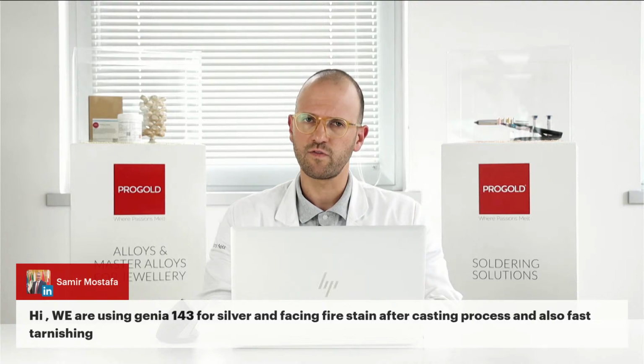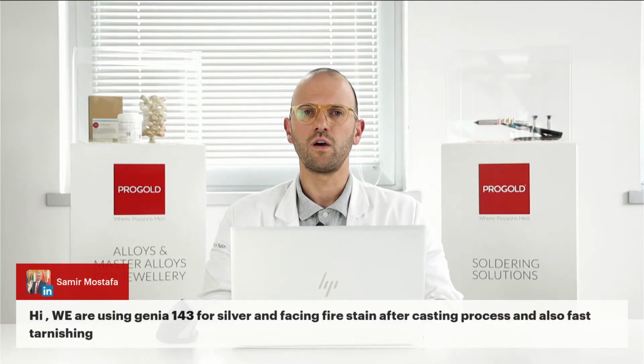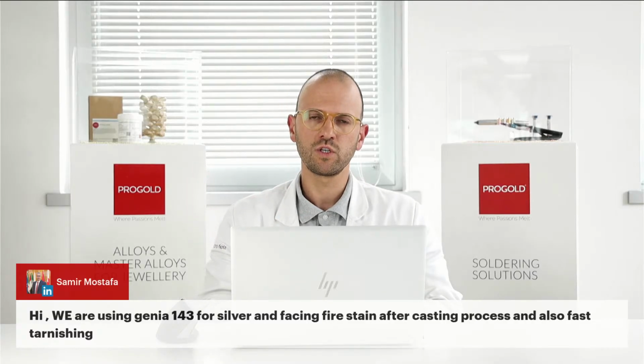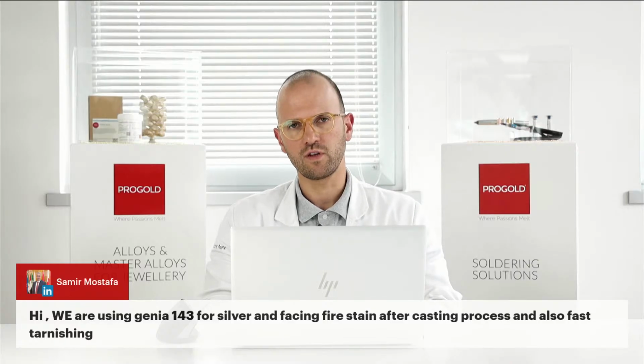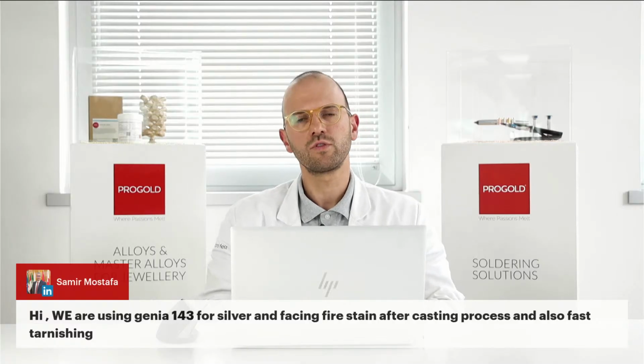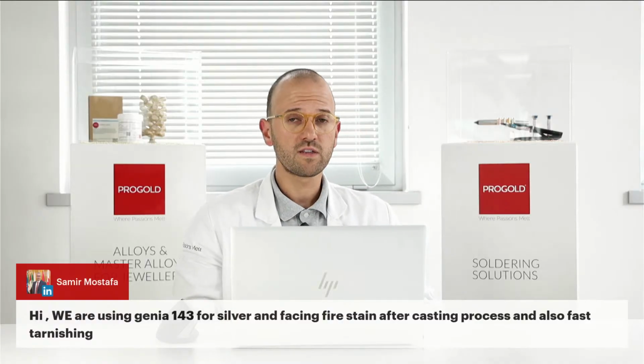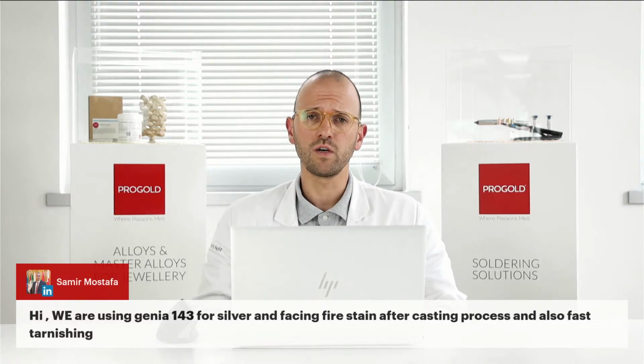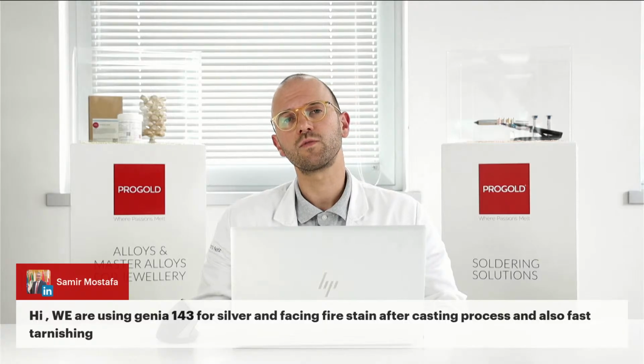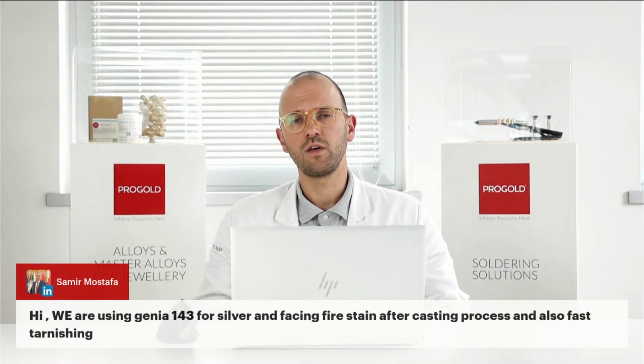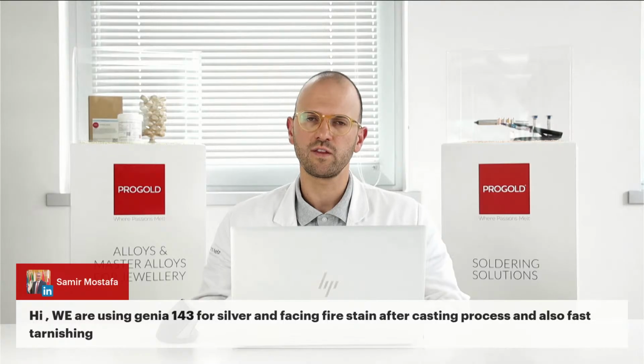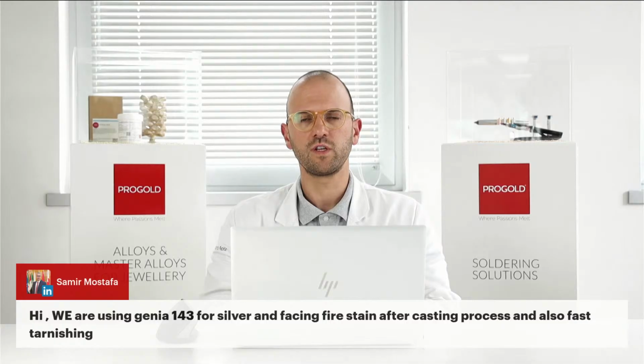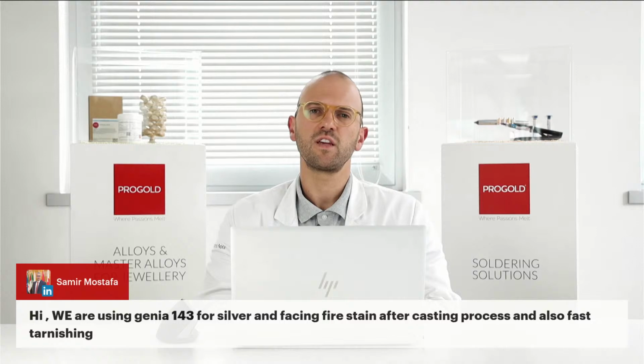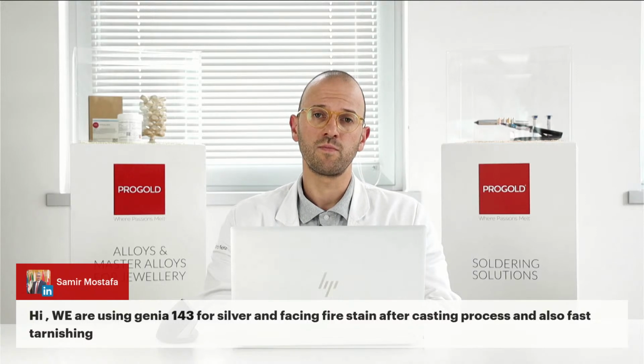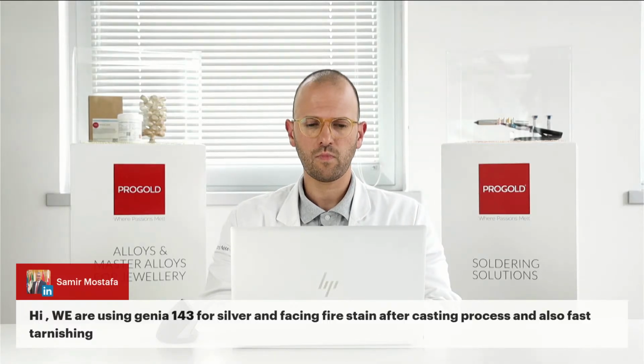Since firestain is an oxidation that occurs with high metal temperature and oxygen, it is also advisable to maintain the flask after casting inside the casting furnace in order to prevent contact between oxygen and the hot metal. The fast tarnish could also be addressed: it is advisable to clean the item as much as possible after the polishing phase with a detergent solution, in order to prevent contact of the surface with the acid used for the production, and to maintain it in a safe environment to protect the surface from the external environment.